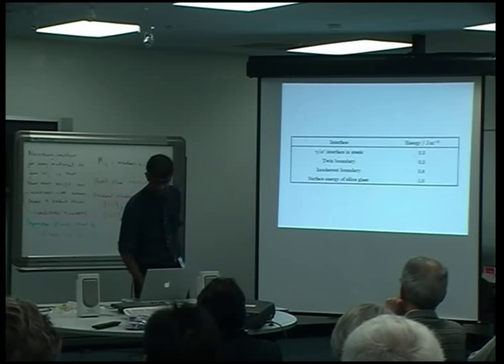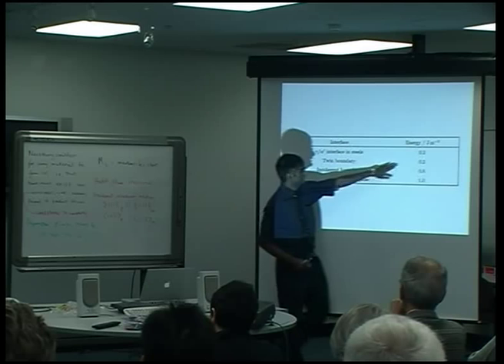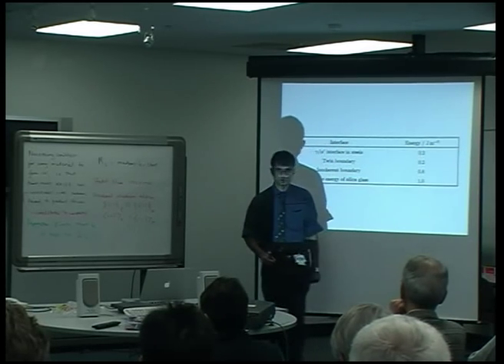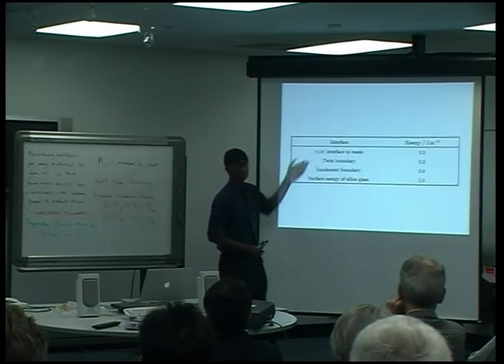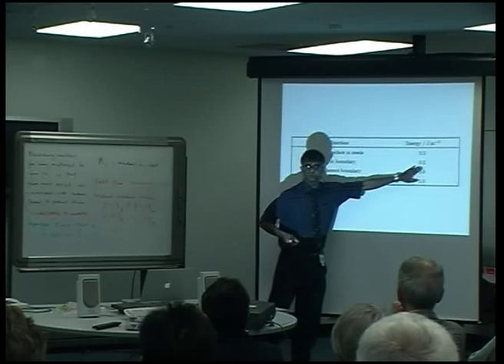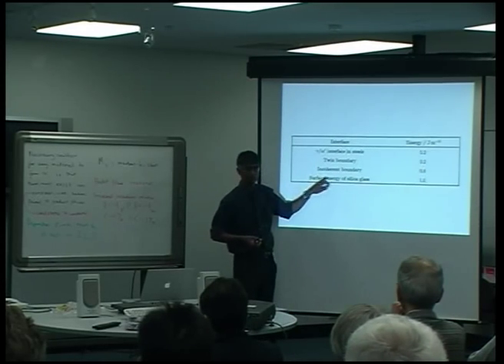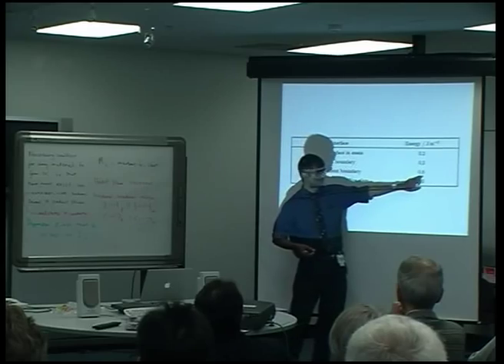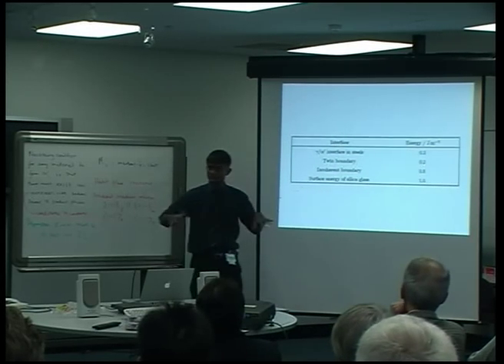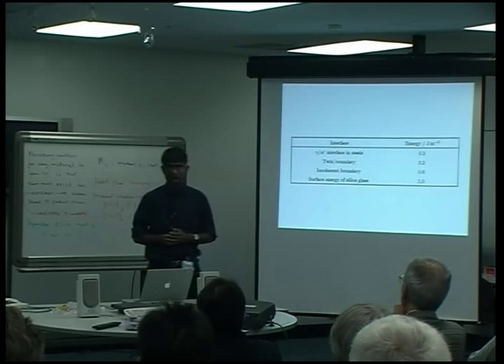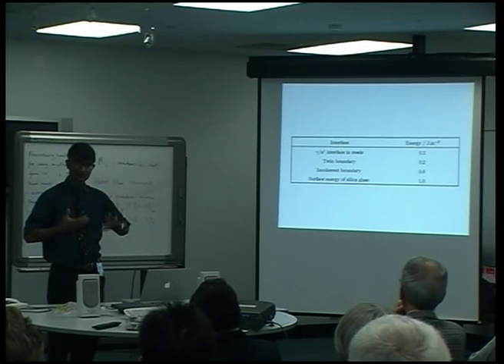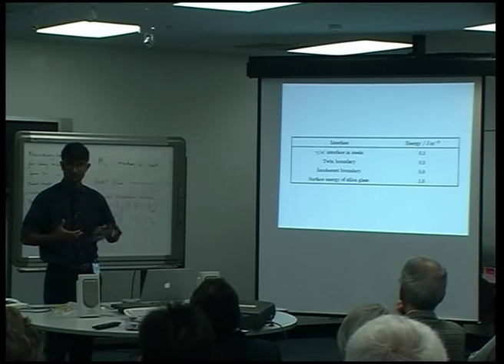This interface is a very low energy interface — it has only one set of dislocations and full coherency along the invariant line, so the interfacial energy is quite low. Typically the interfacial energy of martensite in steel is about 0.2 joules per meter squared, very comparable to twin boundaries. A normal grain boundary would be of the order of 0.8 joules per meter squared, and the surface energy of silica glass is of the order of 1 joule per meter squared — showing we have a lot of coherency in the martensite-austenite interface.